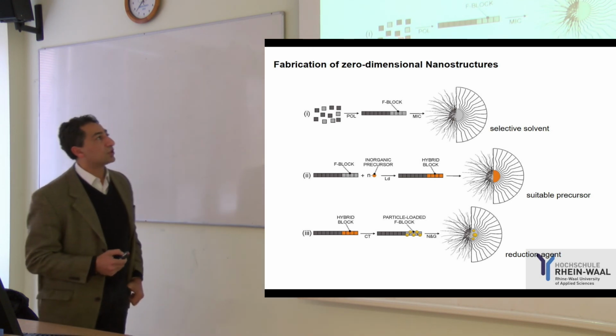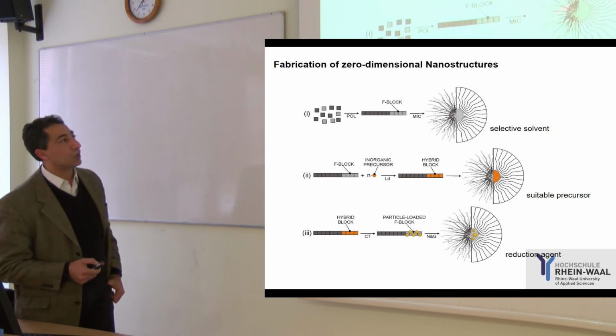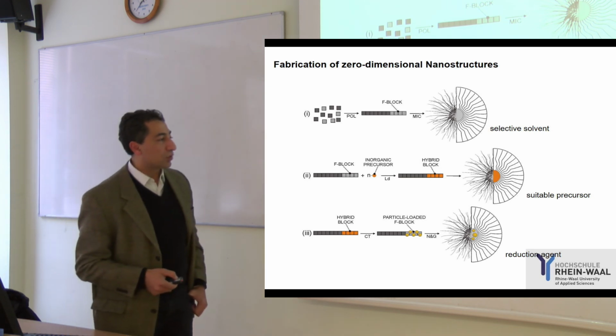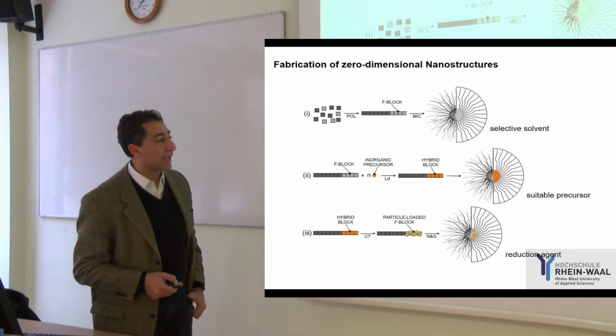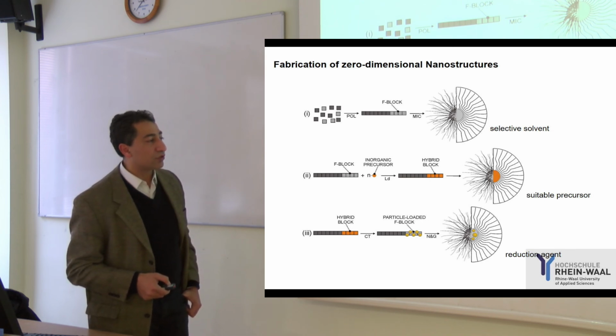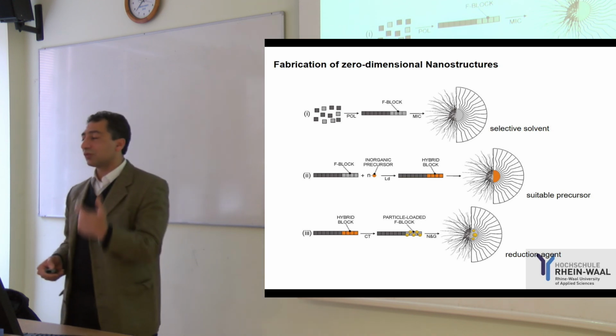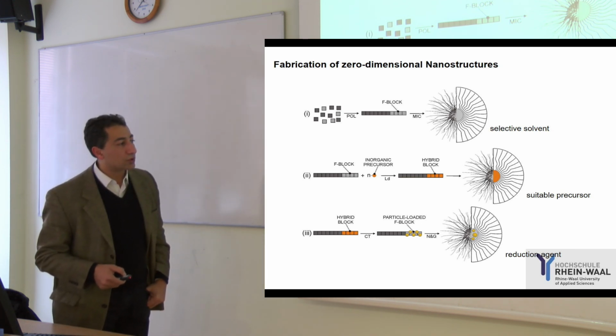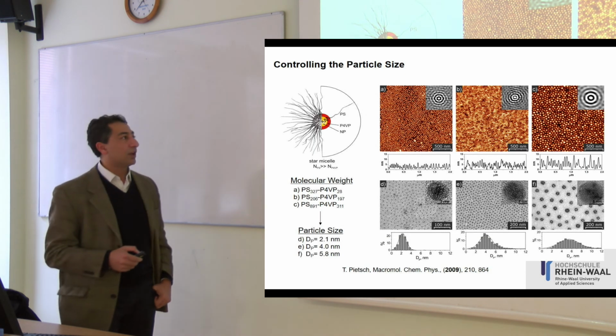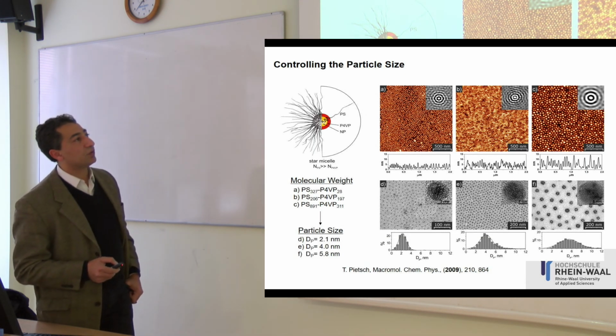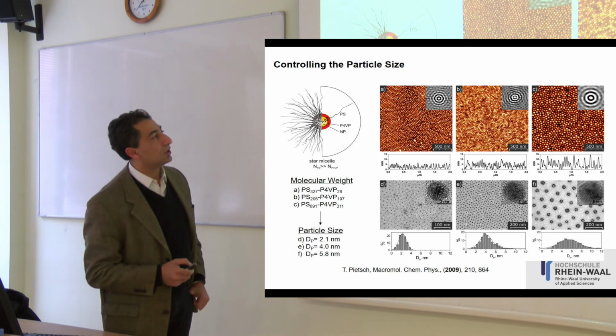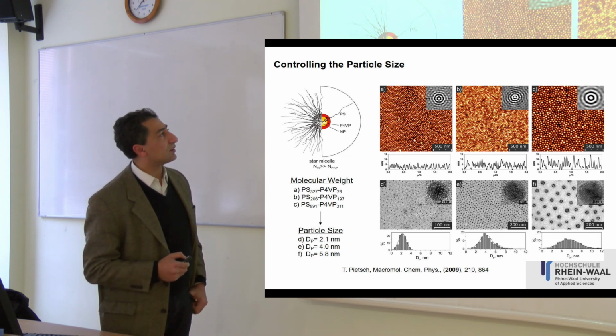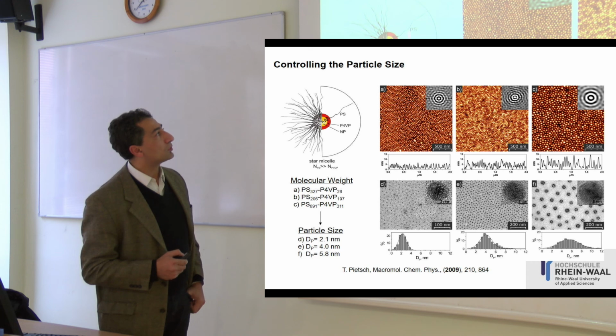We made this simple structure. We have block copolymer. We put the block copolymer in what we call a selective solvent. We put the inorganic inside one of the polymers, and we will have what we call a core-shell structure. The core-shell structure has the inorganic functional material in the core. As we mentioned before, it could be noble metal, semiconductors, or magnetic material, and this is coated with different levels of organic matrix. As you see here, in the atomic force microscope image, you can see the 0D core-shell structure aligned in 2D levels, with the inorganic inside coated with the polymeric structure.